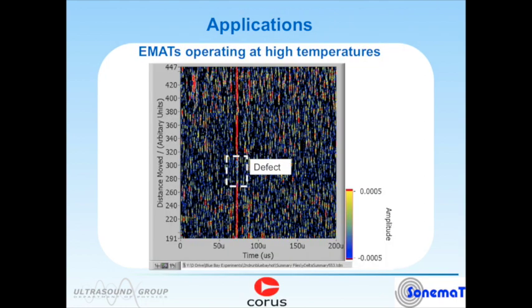The red line you can see down the middle of this plot represents the Rayleigh wave arrival. And what's happening as you look down this plot, the region where the defect passes under the EMAT, you can see there's a clear reduction in the signal, an indication that there's a surface breaking crack. But by looking in more detail at the frequencies that have got under that crack, you're able to say something about the depth of the crack, not just that the crack is there.